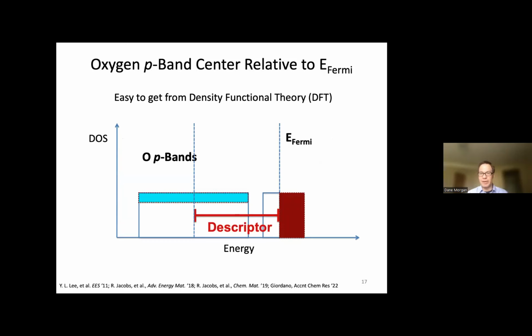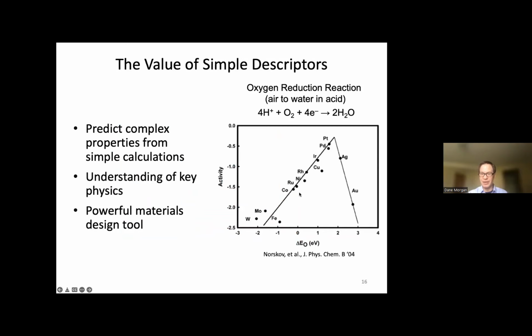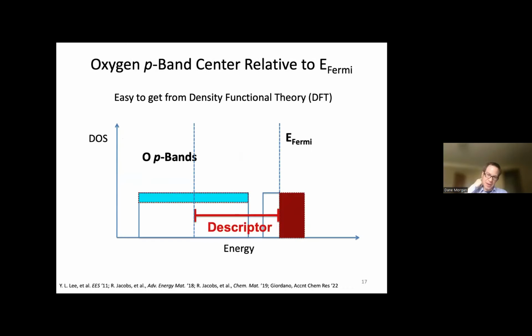Now, we were working with oxygen, not with a metal. And we actually tried the D-band as a descriptor, which is a common descriptor people use and Norskov has used many times. So you may have heard of that descriptor, but we found it didn't work as well. And what we realized is because we're working with oxygen, we needed a feature of the oxygen that might work well as a descriptor. So what we settled on, and I'll show you that this works reasonably well, is what's called the oxygen P-band descriptor.